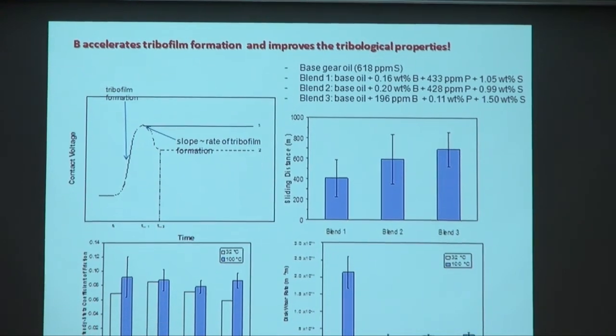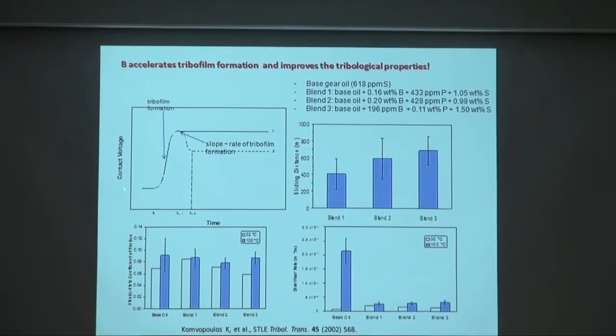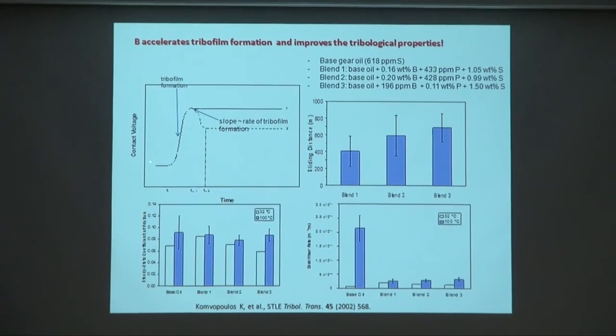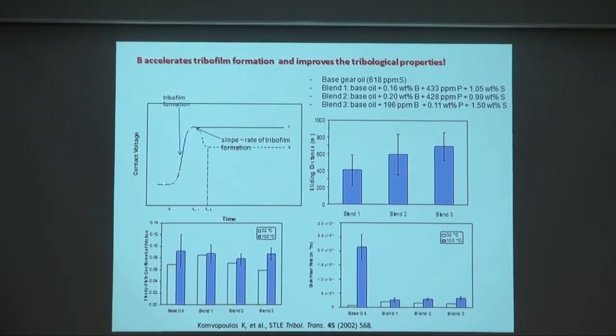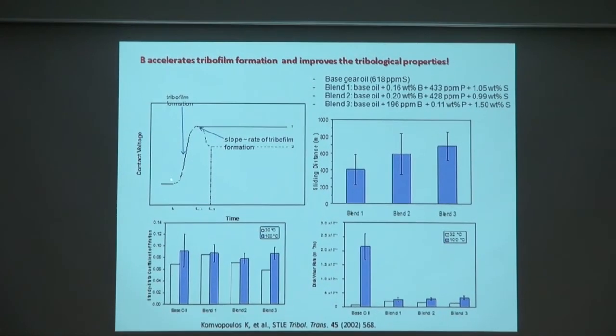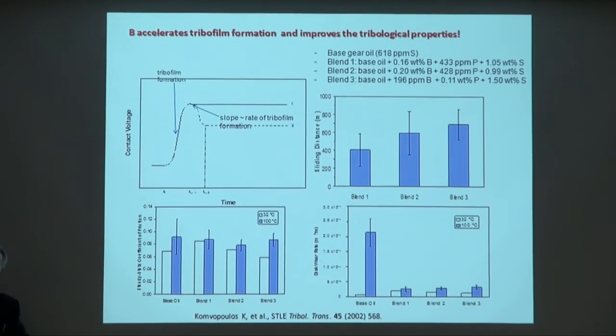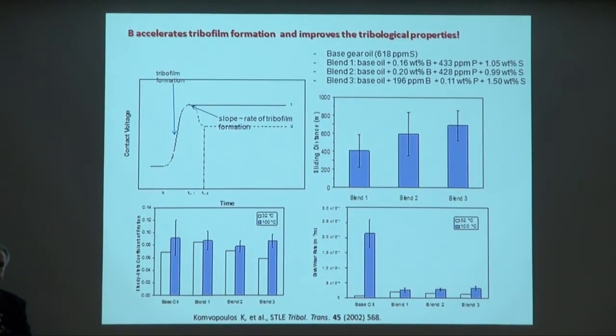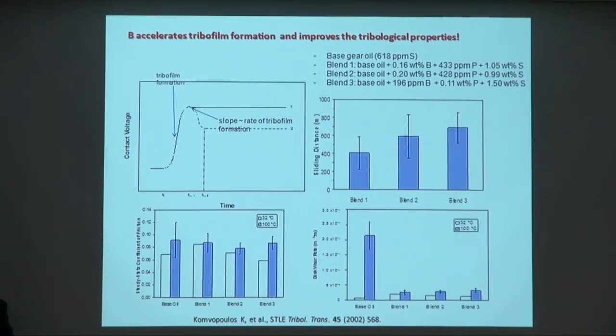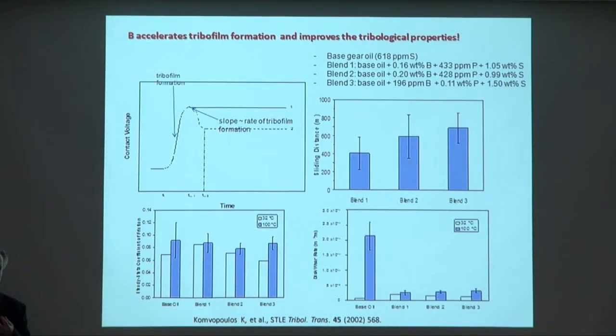So to further understand this tribofilm formation, we can say that the friction coefficient or the contact voltage has an incubation period where the surfaces become activated. When you have rubbing, the two surfaces will be electrified. You will have charges that are building up there. The formation of these charges can contribute to catalysis when the molecules of these additives break apart and you have charges there. This can contribute to reaction. So that takes place in this range.